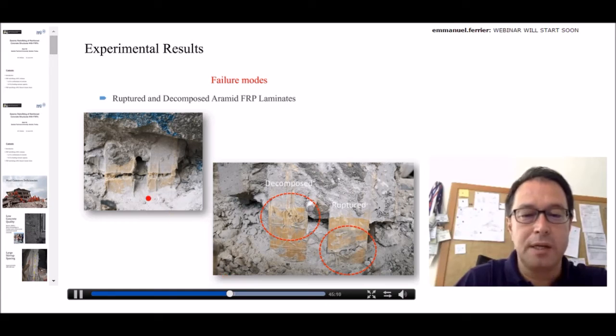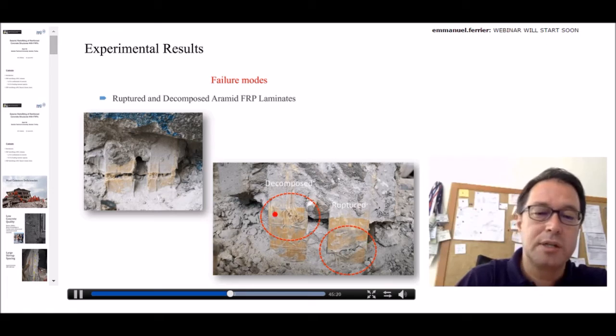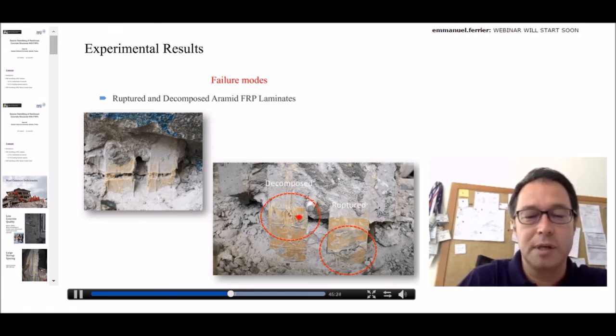Here you can see the failures of the laminates. These are aramid laminates. Sometimes we have total rupture. Sometimes we have a kind of decomposition of the fibers, but not total loss of strength. Of course, that's a better behavior, because rupture is quite sudden, whereas strength is lost a little bit more gradually in this case.